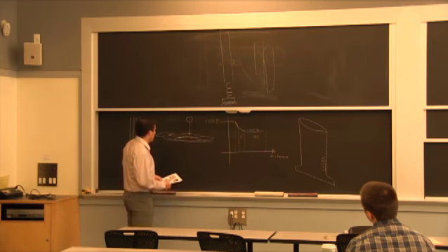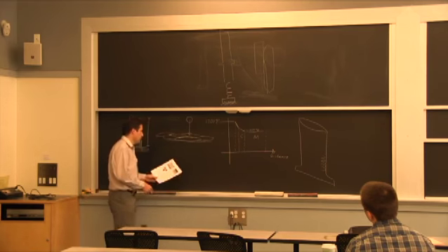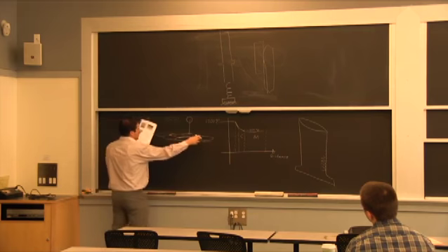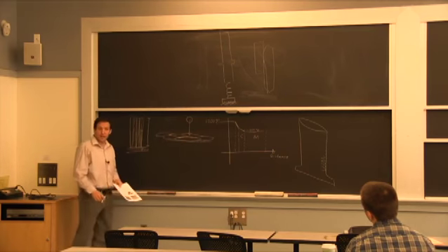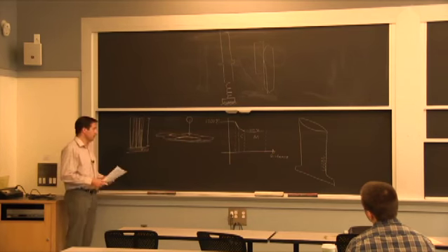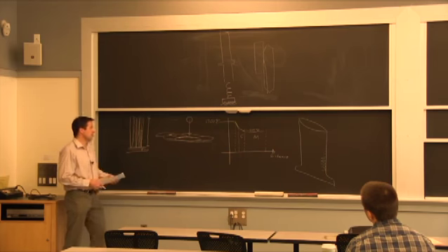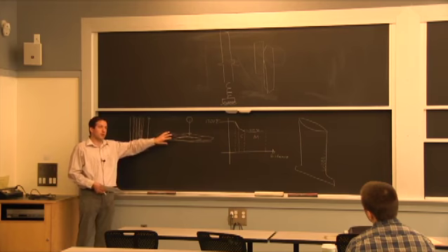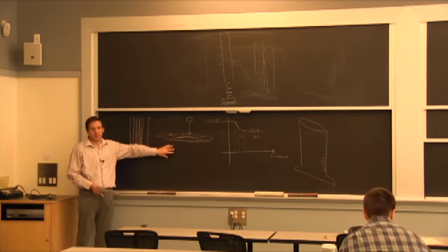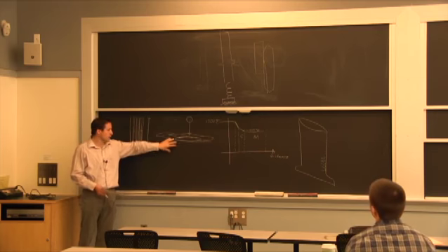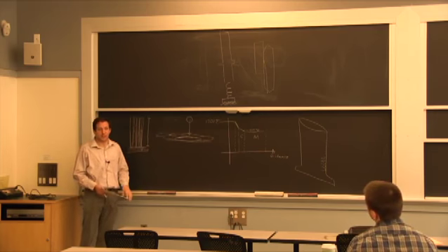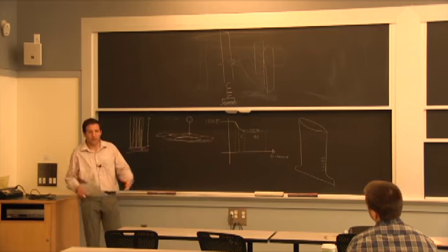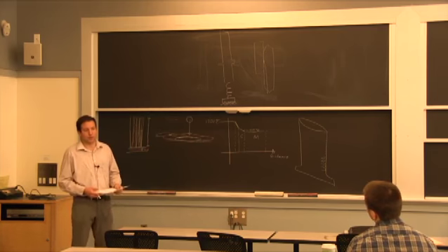In terms of resisting a differential thermal expansion, so a tension and compression going this way, it's really not as good. So you can have a lot of issues of cracking. When you build this microstructure, typically you have a lot of residual stresses. It's a little bit like welding, because you have a cold substrate and you're building up on top of it with something that's hot. It's going to cool down and create shrinkage forces.